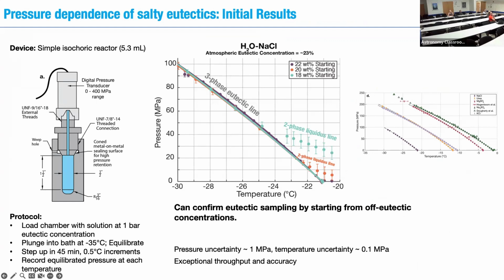So we start from the eutectic composition. We hope that when it crystallizes, we're getting both the crystalline phases and we're getting the eutectic configuration. But you can always check by running the same test with an off concentration, like a couple percent higher or lower than the eutectic. And if indeed you were measuring the 3-phase eutectic in the first place, those 2-phase lines must join the 3-phase line. They must all converge to the same line, right? And that line, if all the 2-phase lines converge to it, is definitionally the 3-phase eutectic line. Does that make sense?